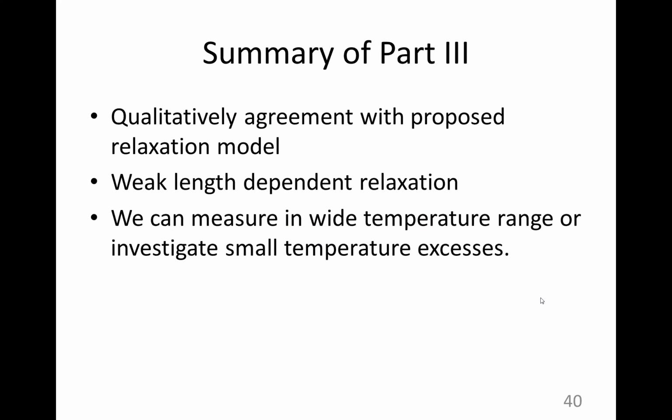So this is the summary of the third part. We obtained qualitative agreement of our experiment with the proposed relaxation model that consists of electron-phonon coupling with diffusion. We observe a rather weak length-dependent relaxation, at least not as strong as we expect from the model.